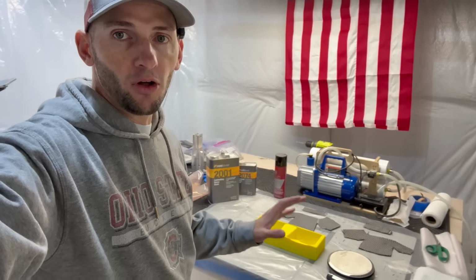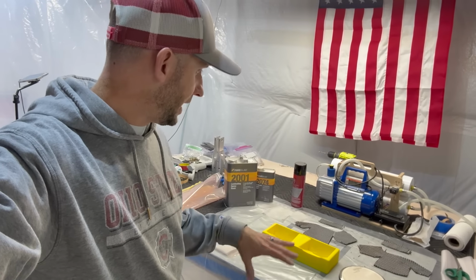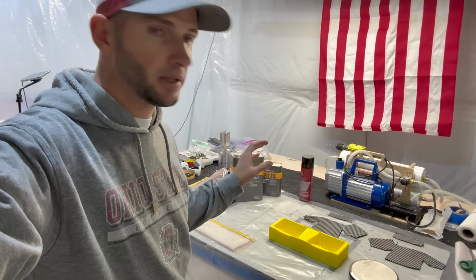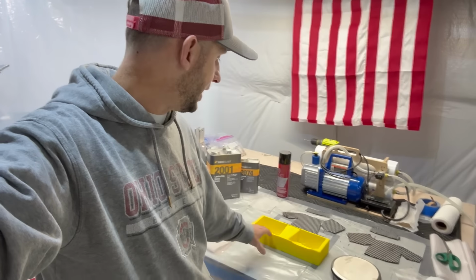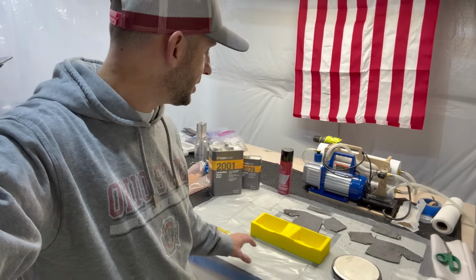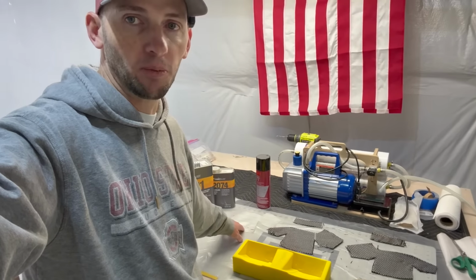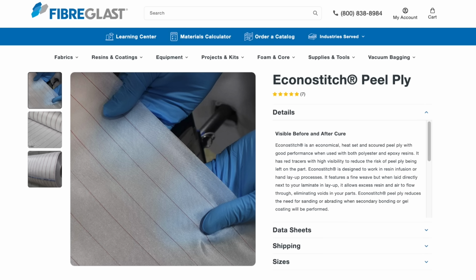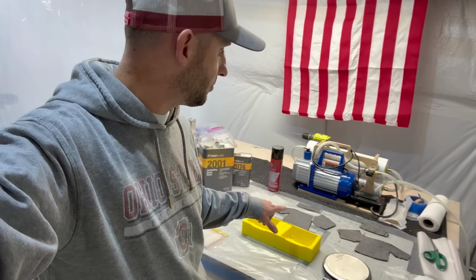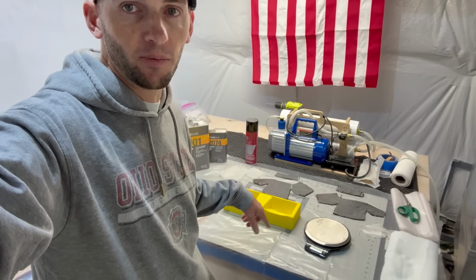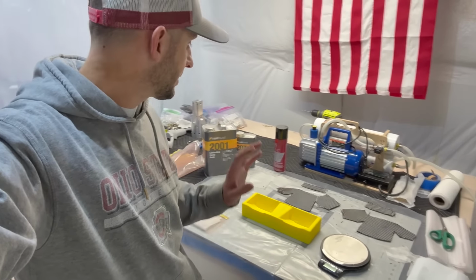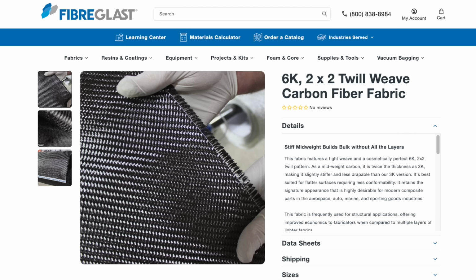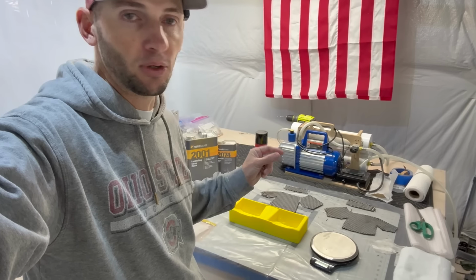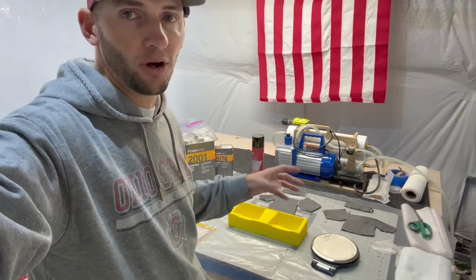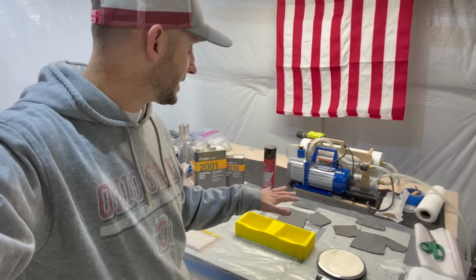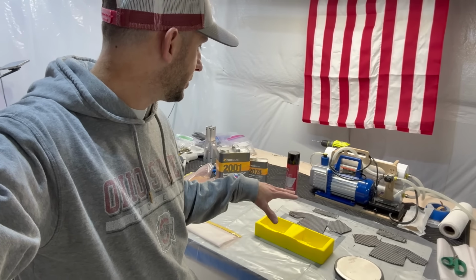All right, I think I've done all the prep work for this layup. So let's touch on all the materials quickly and the game plan. PLA mold, that's going to be released with just a layer of peel ply. That peel ply is from Fibreglast. We're going to make the layup out of 6K carbon. You can see the templates cut there. I was going to start with 6 layers and then do 12 on the face for bulk. I've reduced that down to 4 and 4. I just think 6 was overkill. So that's 6K carbon, 2x2 twill.